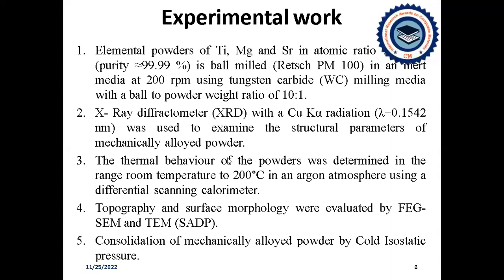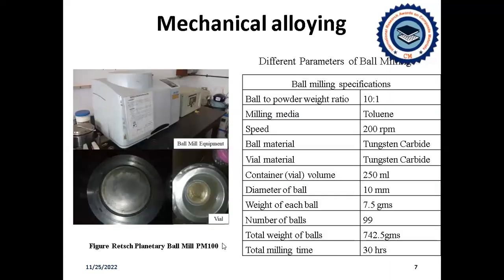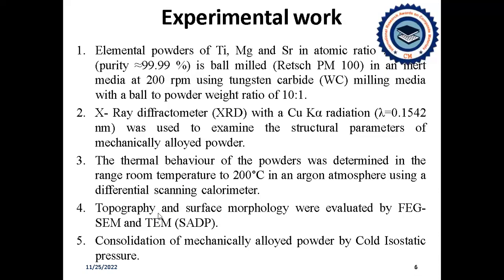Using the X-ray diffractometer technique. Also, the thermal behavior of the alloyed powder and the compact sample was determined at room temperature using the DSC. Topography and the surface morphology were also evaluated by the SEM and the TEM SADP pattern. After alloying for 30 hours, the alloyed powder particles were consolidated by cold isostatic pressure, and then similar characterization was performed in order to know the structural parameters and phase evolution of the compact sample.